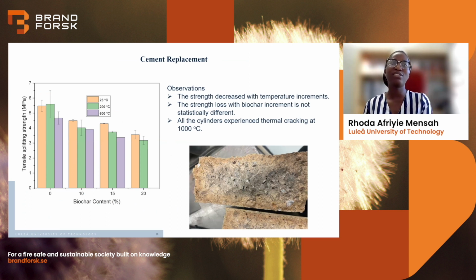We also did the tensile splitting test for the cement replacement samples in the cylinders, and we noticed a particular trend where the strength decreased with increasing biochar content. For this particular result, we don't have any results for 1,000 degrees Celsius because the concrete cylinders crumbled when we tried to do the tensile splitting test. If you look at the figure on the right, we see that it just broke into two pieces when we decided to do the test.